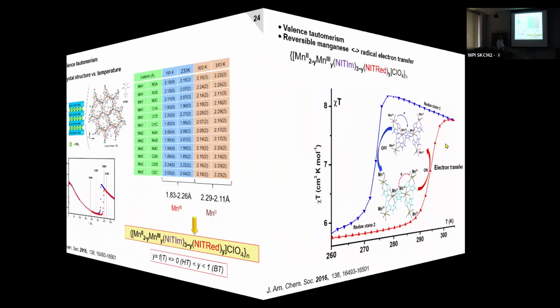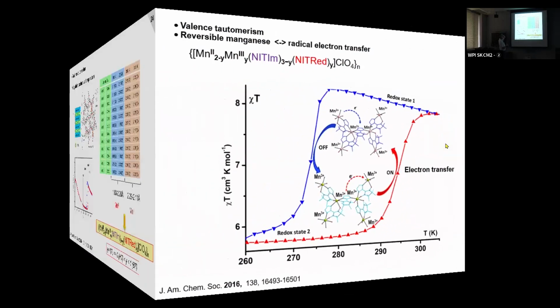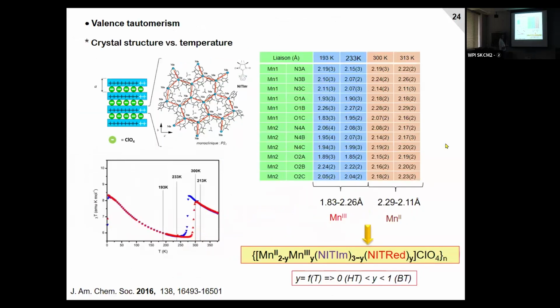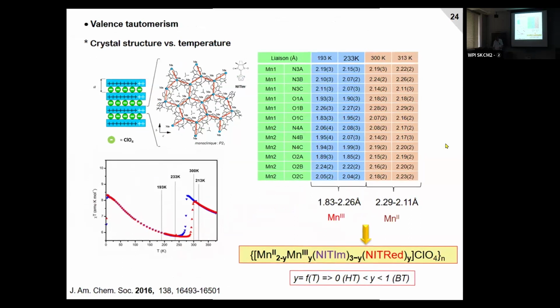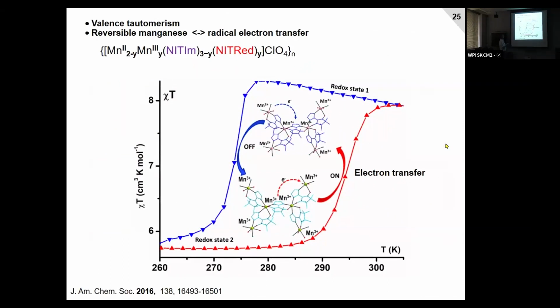And in fact, the formula is not the formula I showed you before, almost. We should write the formula like this. So you have manganese 2, manganese 3, and depending on the temperature, here, it depends on the temperature. Depending on the temperature, you will have manganese 2 or manganese 3. So here you have manganese 2. When you have here the manganese 3, some electrons of the manganese go to the radical. Manganese is oxidized and some radicals are reduced, but you have to keep in mind that you have 2 manganese for 3 radicals. So if you have 2 manganese, you have 2 electrons that go on the radical, but on the radical you have 3. So only 2/3 of the radicals will be reduced.